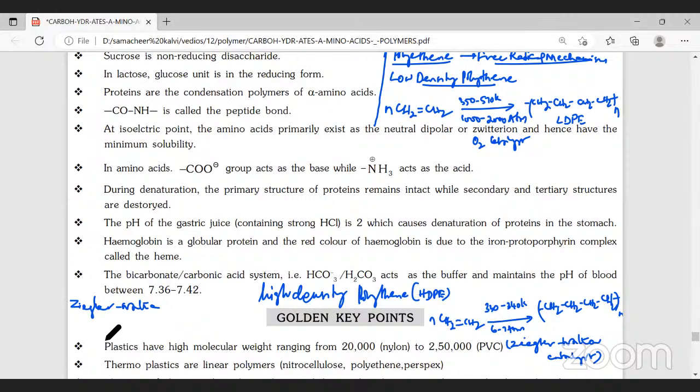Now, this is titanium, or maybe we can write like this, triethyl aluminium. C2H5 is the ethyl group. Aluminium valency is 3. Therefore, triethyl aluminium and titanium tetrachloride is an example of a Ziegler-Natta catalyst. And the solvent they use is heptane. Normal heptane is the solvent.